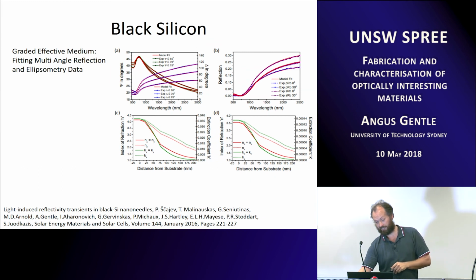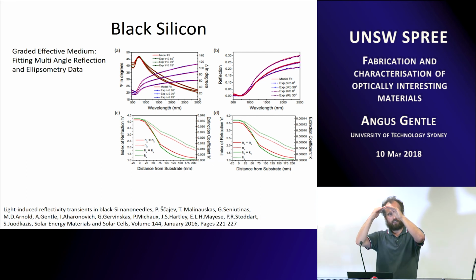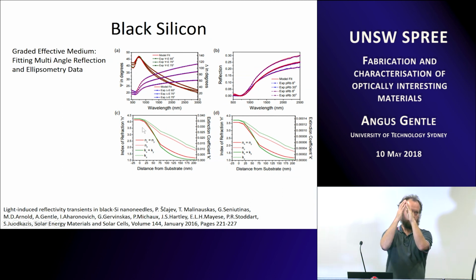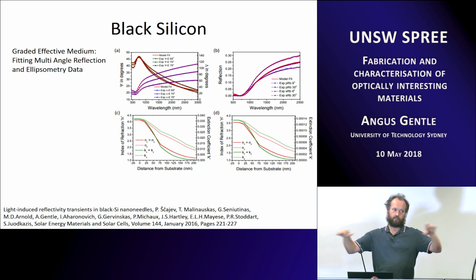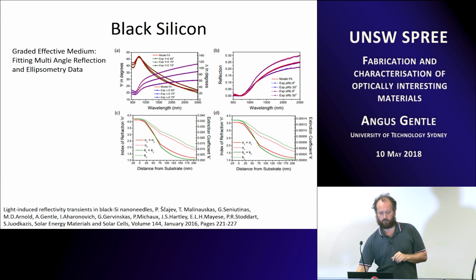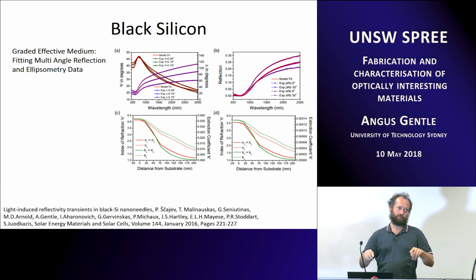So this is basically the refractive index throughout the sample. So if you start at the top and you've got voids, so that's down here, you got voids and then it goes to a basically continuous silicon at the bottom. And so this was combining a tapered effective medium of mixing silicon and air and a very thin oxide as well, and combining ellipsometry and multi-angle reflectance. And so that was a fun one.